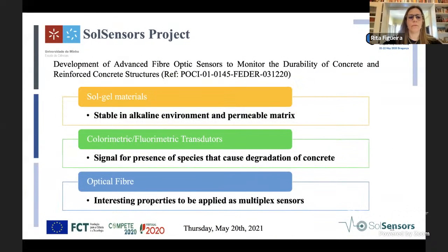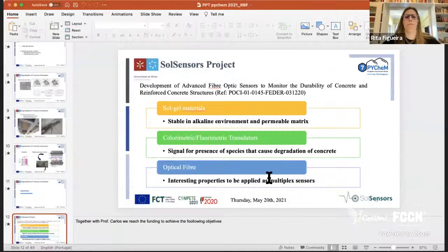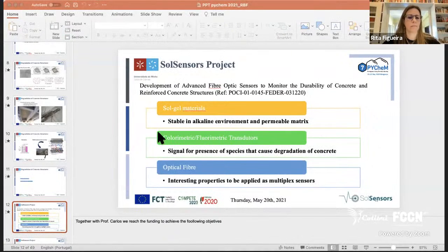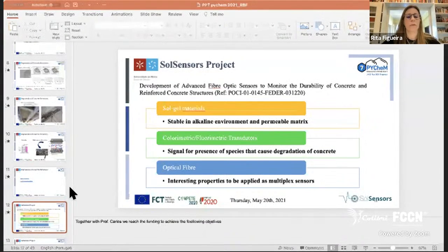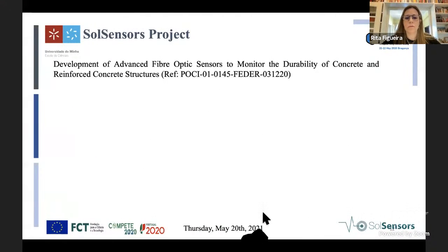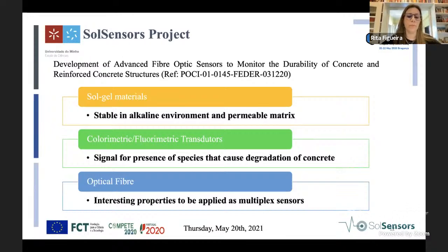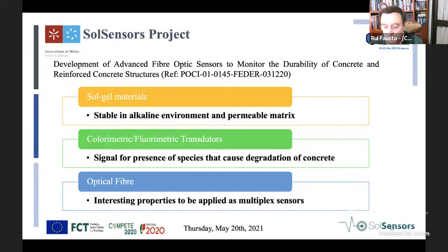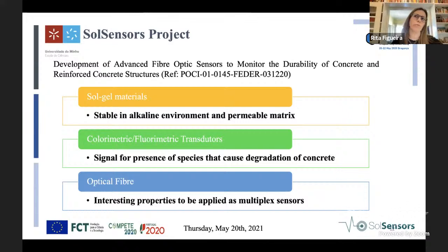So what we are trying to do here is to develop sol-gel materials that are stable in alkaline environment and need to be a permeable matrix, and the signal, the detection of species such as chloride ions, to detect the alkali-silica reaction, we need to detect moisture, detect potassium ions and sodium ions, and pH also, because to control the carbonation of concrete, we need to control the pH.